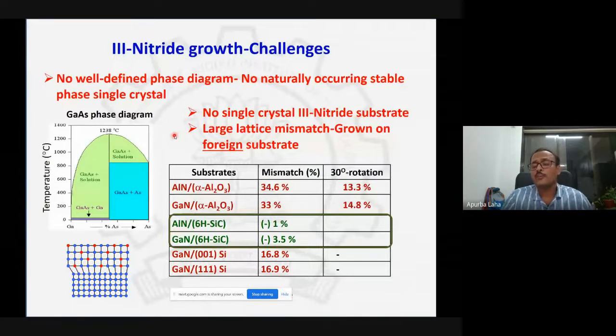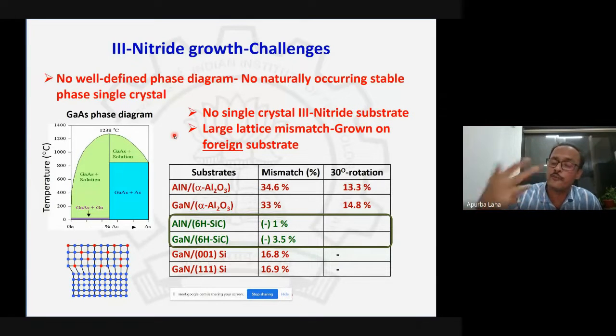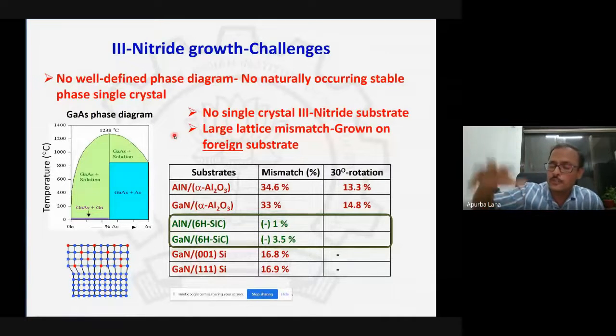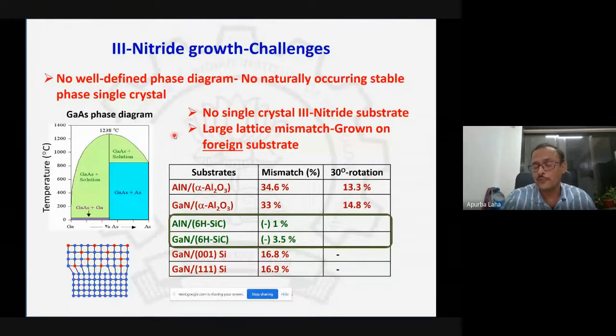Now, for III-Nitrides, you do not have this. There is no such phase diagram if we compare the stability of nitrogen and gallium. So all we have to do is create a situation far away from thermodynamic equilibrium, and then create a process condition that favors the formation of gallium nitride. Now that is one challenge, the formation of gallium nitride crystal. Because there is no gallium nitride crystal formation naturally, as there's no phase diagram as such, you don't have a single crystal gallium nitride substrate.